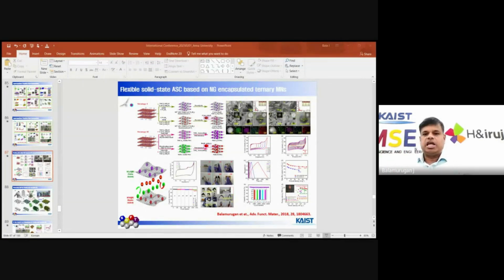And we studied the optimal potential by varying the potential from 0.4 to 1.6. Even if we go beyond 1.6, some oxygen evolution happens. Therefore, we stopped at 1.6 because it is aqueous media, and we get different scan rate effects and charge discharging. And we also compare with activated carbon as the negative material, because when you go for negative material at high current density, maybe the rate performance will be low.